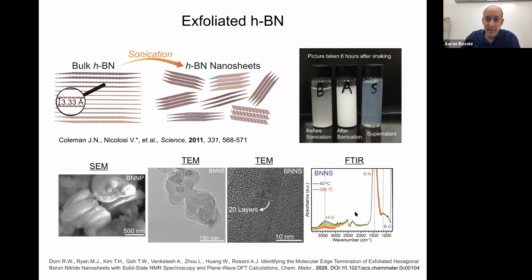Now, we did some basic FTIR characterization. We can see some stretching signals possibly associated with hydroxyl groups and maybe amine groups. And we can also see some BO stretching frequencies. So that tells us the edges are likely partially oxidized during the course of this exfoliation.